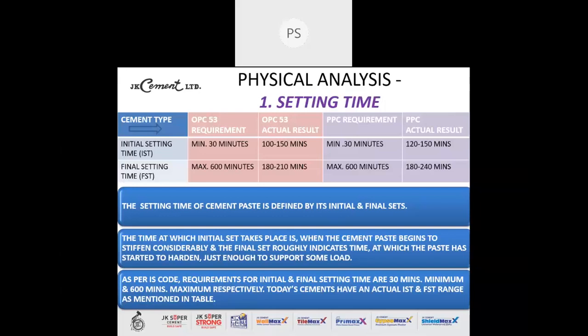Now, if you look at the PPC cement, the requirement is same, minimum 30 minutes and maximum 600 minutes. In India, the actual results for initial setting time for PPC are between 120 to 150 minutes, and for final setting time for PPC are between 180 to 240 minutes. Now we look at the points below.